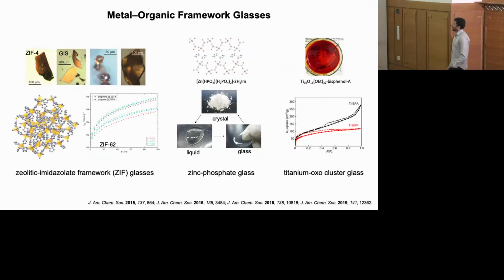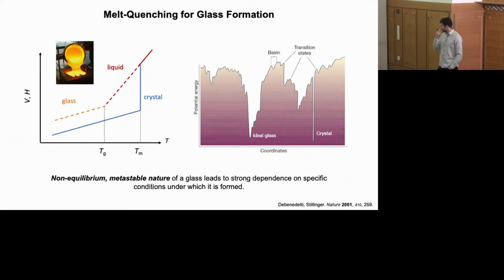But getting a metal organic framework type material to undergo a transition from the crystalline solid state to a liquid that can be quenched into a glass is really not an easy task. There's only a few examples of different types of metal organic frameworks that undergo transitions to form a glass, and most materials will thermally decompose before they undergo a melting transition.